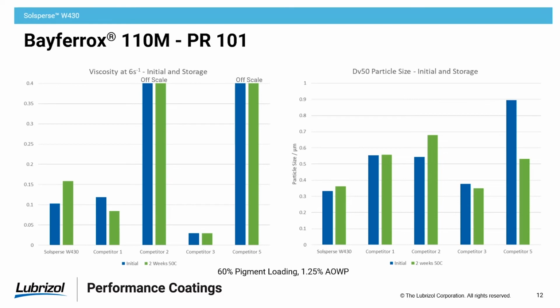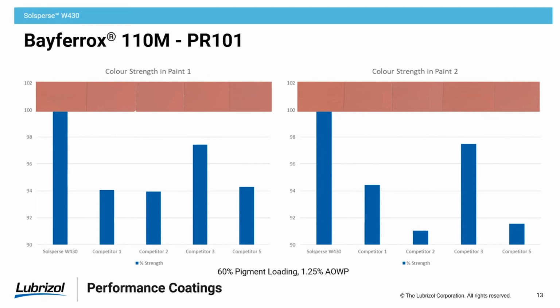But making a low viscosity and low particle size dispersion is just your start. At the end of the day, what we need is to have good color strength. Here we have these tints, the 1 to 10 tints that I described before, in 2 commercially available acrylic latexes. And here we have W430 always being the control, 100% tint strength, and comparing to the other dispersants, some of which in the previous work would have shown perhaps lower viscosity, but also lower tint strength. So across the board, for this particular grade of red iron oxide, the W430 is a pretty good performer at a very, very reasonable dispersant demand of only 1.25 additive on weight of pigment for a 60% pigment grind.